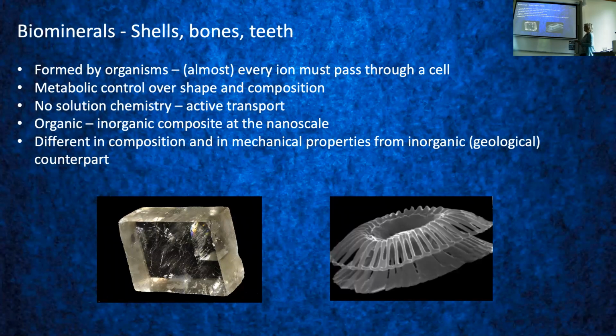And what you also get is that these biominerals always contain a certain fraction of organics as a coating, but also within the crystal. While they diffract with X-ray diffraction, for the longest time people thought they were single crystals because they diffract like a single crystal. What we know today is that there are multiple highly aligned twins. So they're poly twins, little crystals that diffract as a single one. And because they're mixed in between organics and inorganics, they have very different properties to their geological counterparts.